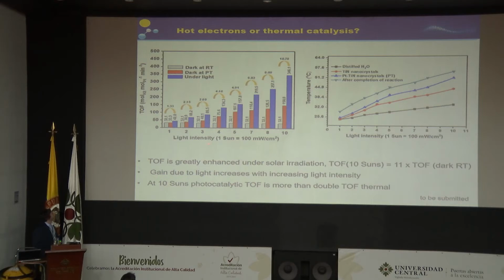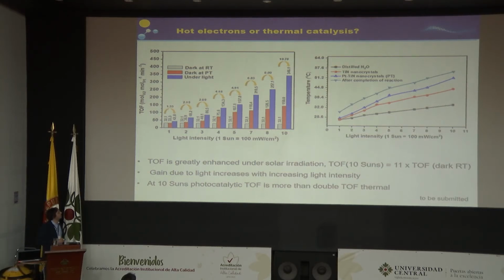Here we studied, with concentrated solar light, the hydrogen production from ammonia borane using different light intensities. You can see the dark temperature, so room temperature in the dark. This is the activity of hydrogen production from ammonia borane with our catalyst in the dark. Then by shining the light, we can have about 10 times higher activity of hydrogen production with our photocatalyst. The thing is that when you shine the light, you can create a significant temperature increase, and so this also changes the dark chemical reaction rate.